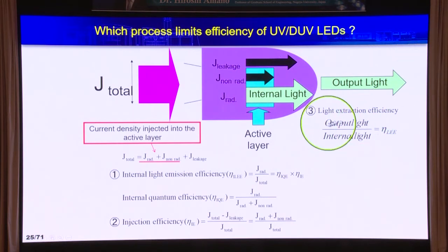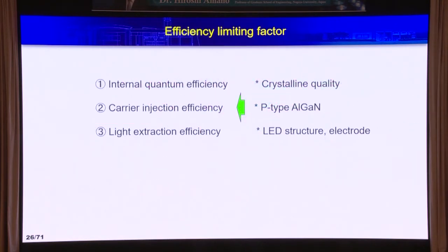And the third term is the light extraction efficiency. Because for the semiconductor material, the refractive index is higher than 1. The air is 1. So not all the light can be extracted from the semiconductor to the air. This is called the light extraction efficiency. Of these three terms, internal quantum efficiency is related to the crystalline quality. Carrier injection efficiency is related to the p-type hole concentration in aluminum gallium nitride, and the light extraction efficiency is related to the LED structure.